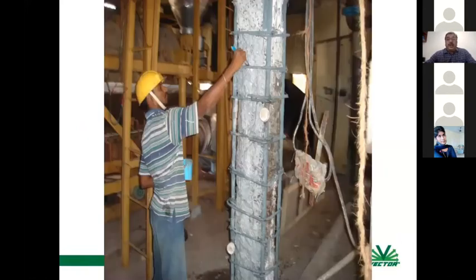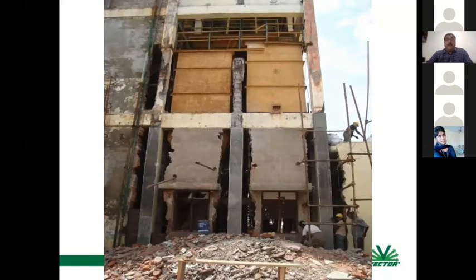Here again, the anodes have been installed, and then zinc-rich epoxy coating has been applied. But obviously, spacing is very high. This was done about 10-12 years ago. I told you that we are now having more rational design, and then the normal jacketing has been done. The only thing is adding this anode, nothing else.